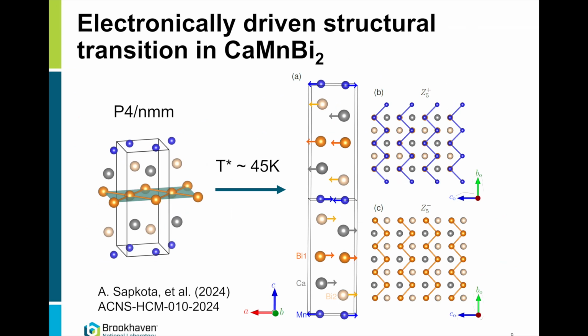Okay. Calcium manganese bismuth 2. In ytterbium manganese bismuth 2, it's probably below 0. So, I mean, it doesn't happen. What I show, the temperature of the distortion is material dependent. And there are materials like ytterbium manganese bismuth 2, which do not show this distortion down to 1.5 Kelvin.